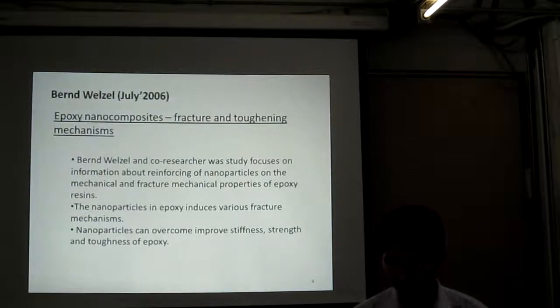Epoxy nanocomposite fracture and toughening mechanism. This research studied information about the effect of nanoparticle on the mechanical and fracture mechanical properties of epoxy resin. Focusing on nanoparticle in epoxy-induced various fracture mechanisms, it found that nanoparticle can improve stiffness, strength, and toughening of epoxy.